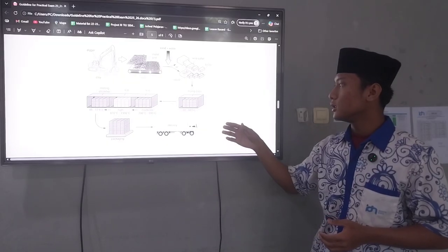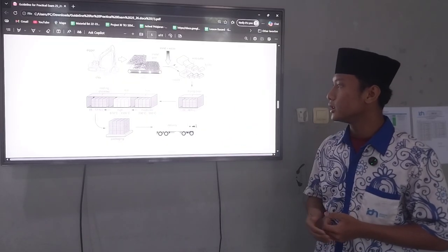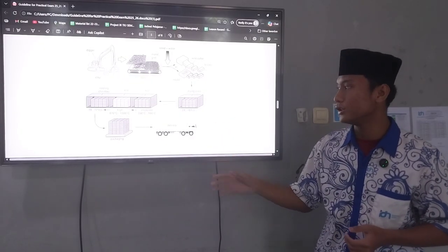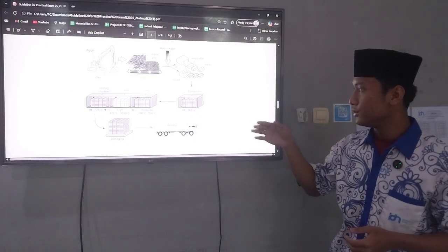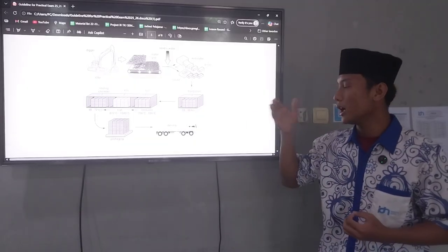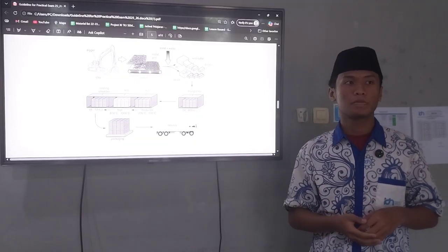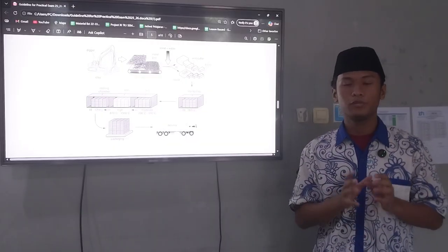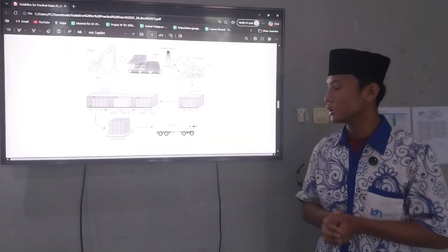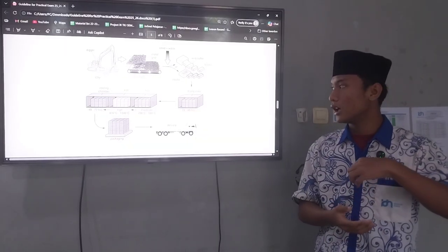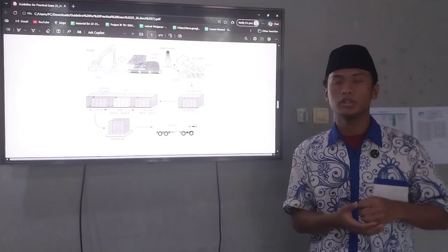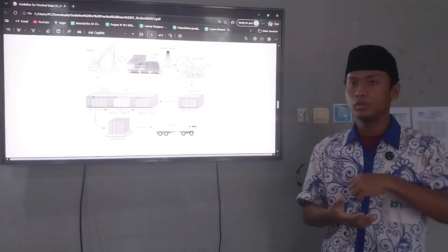And also the high temperature heating is from 870 Celsius up to 1300 Celsius. So after the brick is heated inside the high temperature oven, the brick is not able to face the normal temperature or normal air, because if the brick immediately faces normal temperature, the brick will be broken. And also become weak again.